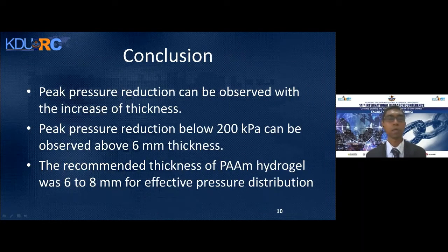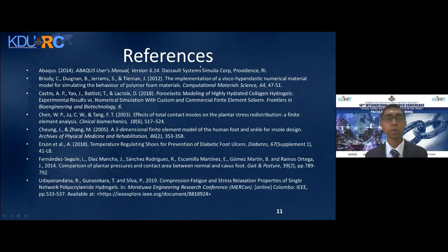So as a conclusion, I can say that the peak pressure reduction can be observed with the increase of thickness, and the peak pressure reduction below 200 kilopascal can be observed above 6 mm thickness, and the recommended thickness for this polyacrylamide hydrogel was 6 to 8 mm for effective pressure distribution. And these are the important references, and the last reference is the one I mentioned, that you can refer to for further details.